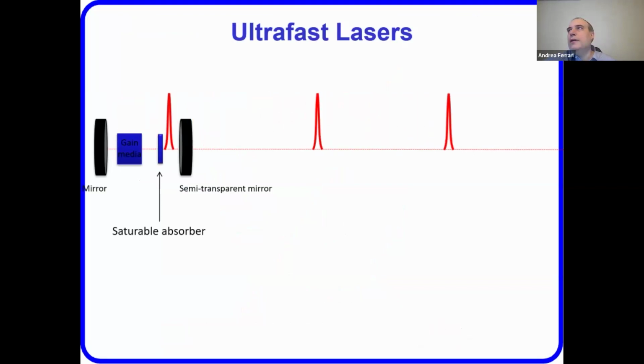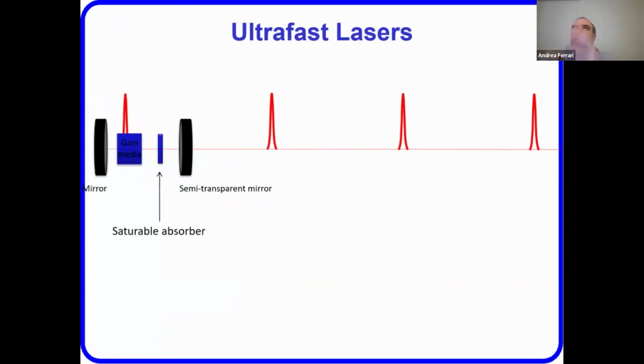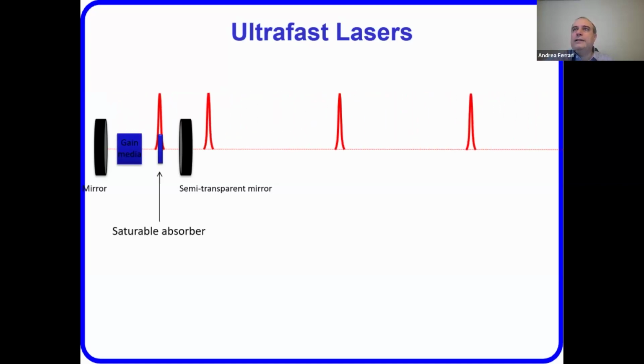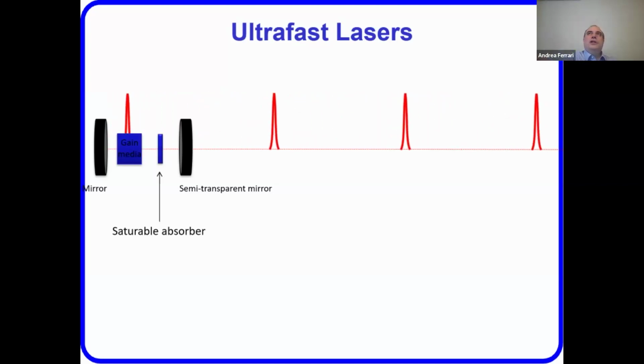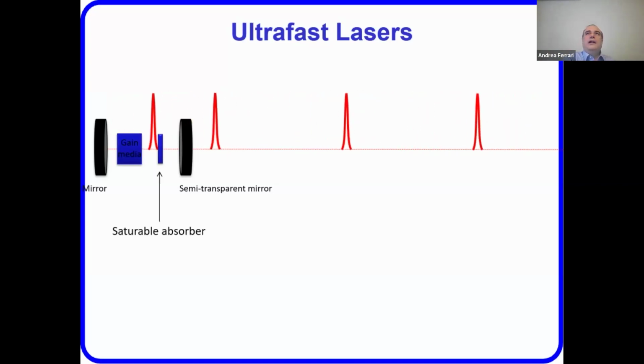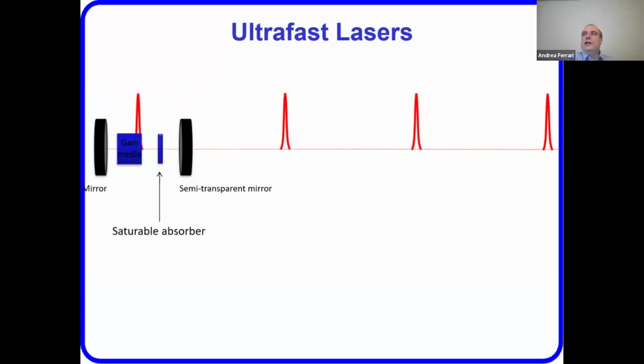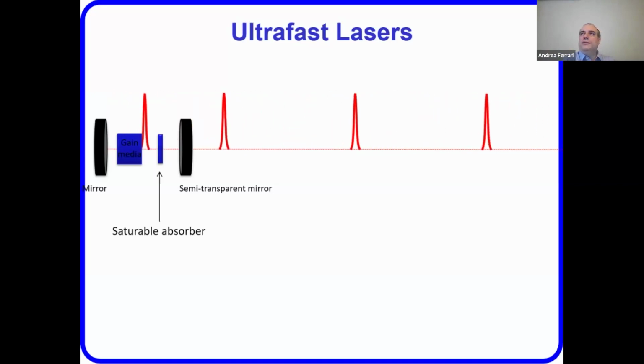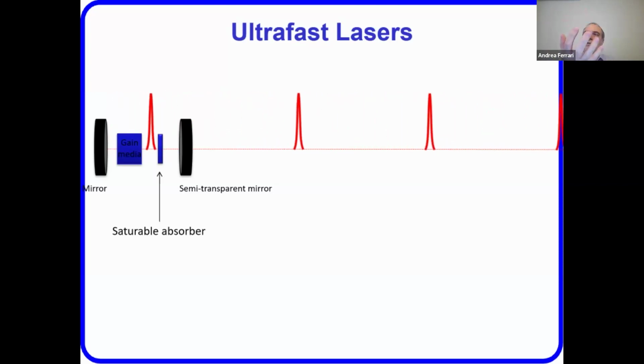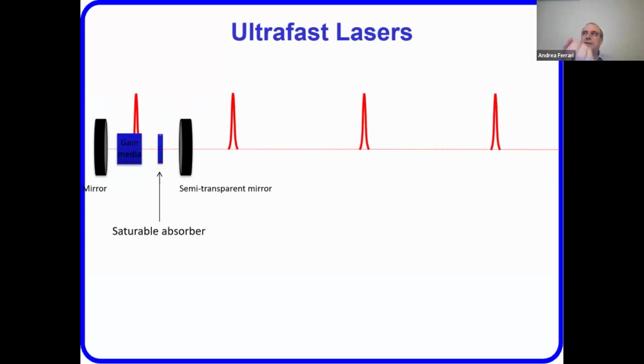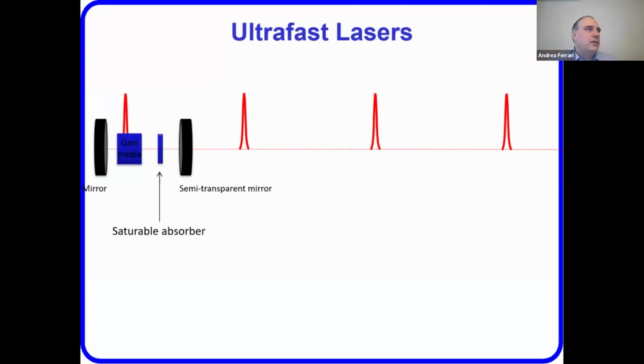A saturable absorber, as I showed before, is a material that absorbs light. When the light is absorbed, it lets light through, and then the light gets absorbed again. It's like a sponge that you put under water, and until the sponge is full of water, it will absorb water. Once the sponge is full of water, the water gets through, and then you have to squeeze it in order for the sponge to work again. The good thing with graphene and other passive saturable absorbers is that the squeezing process happens automatically due to the relaxation.